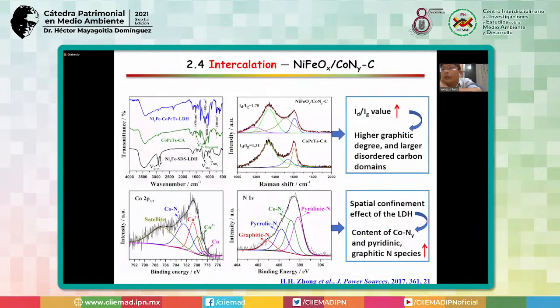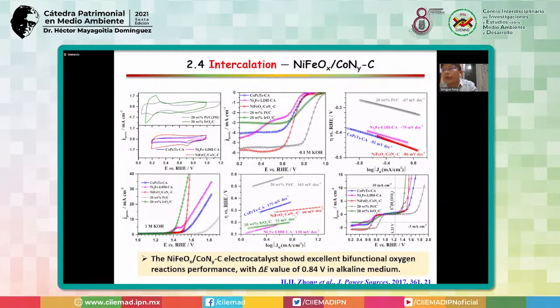And also we can see a higher graphitic degree and larger disordered carbon domains, due to the confinement effect of the LDH. So we can produce a highly increased content of Co-Ng, pyridinic and graphitic nitrogen species. Because they are located in the interlayer species, after we calcinate, we get a higher content. So it is also good for the oxygen evolution, and we get very nice, excellent bifunctional oxygen reaction performance.